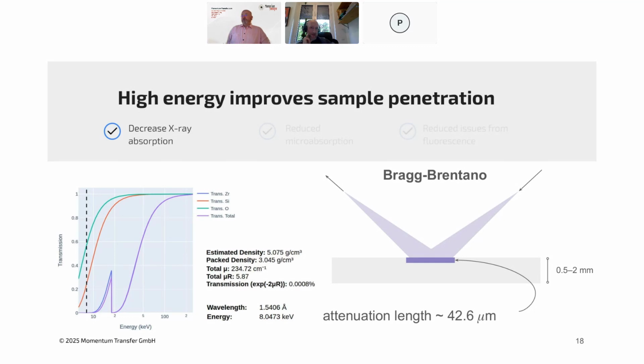from passing through. So if we're working with a Bragg-Brentano system, which is a reflection geometry, your X-rays are incoming to the surface of your flat sample and then outgoing back in the other direction. And so a typical flat plate sample might be prepared with a thickness of about 0.5 to 2 millimeters of powder. And actually your X-rays are only diffracting significantly from a very thin surface of this. So if your material, for instance, is not very homogeneously mixed, if you have some much larger crystallites or particles in your sample, then you're significantly biasing the material that you're actually probing in your sample. Okay, so this is not very ideal.